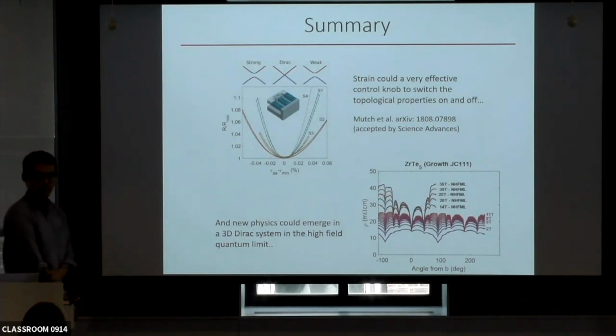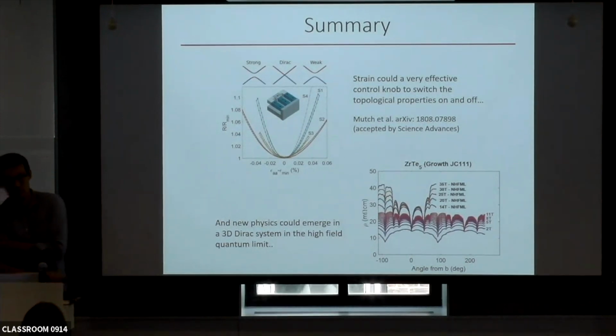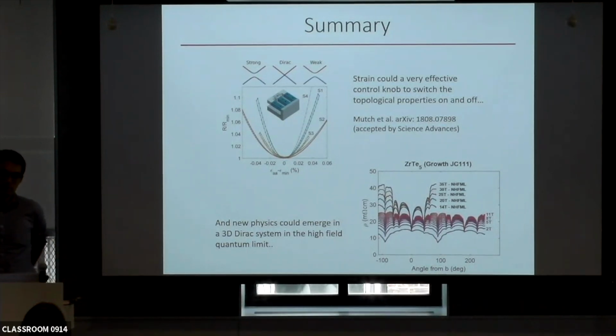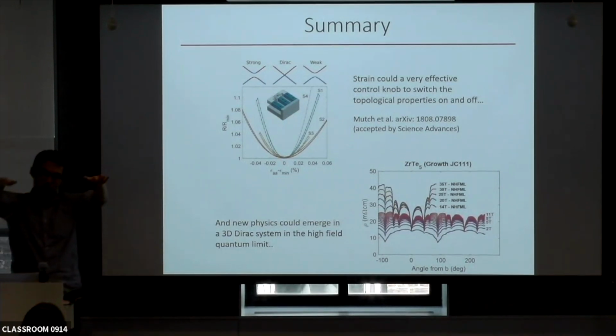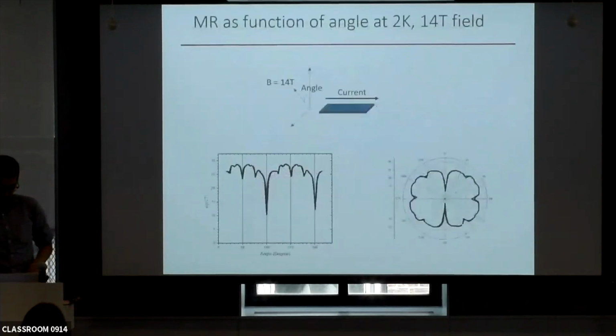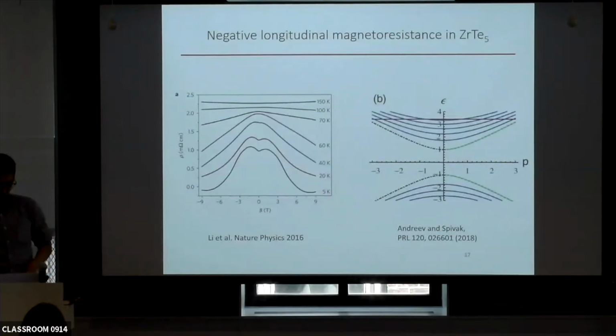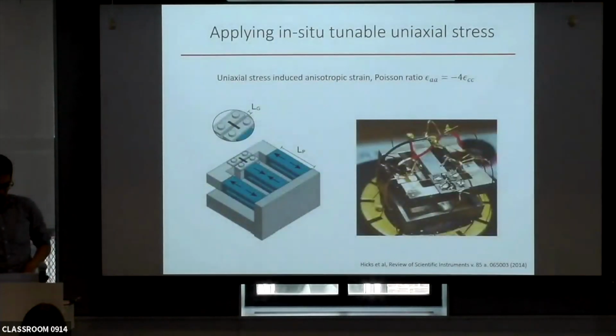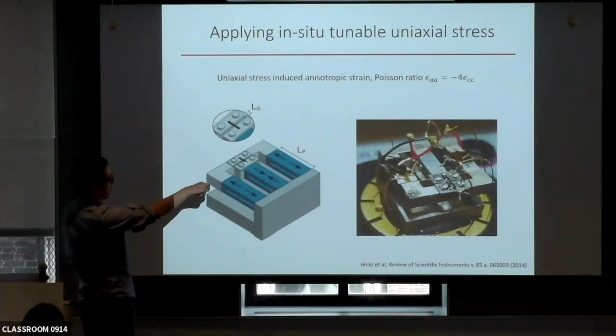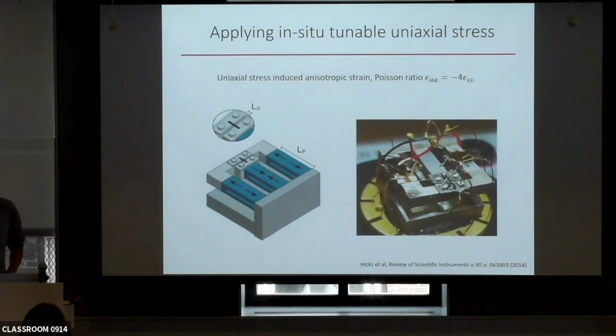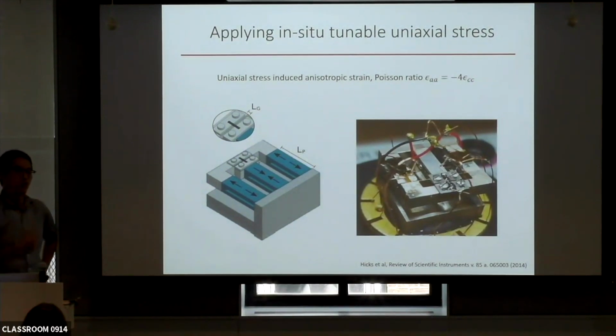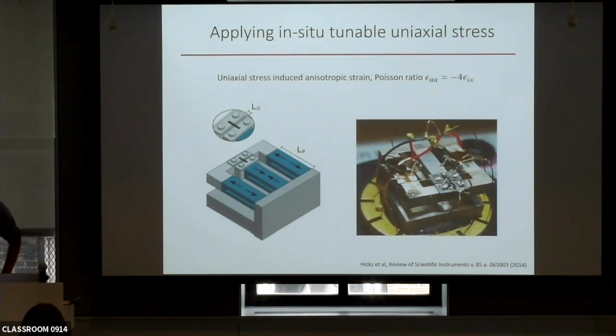Very interesting. On the first part, for the zirconium pentatelluride, as you said, it's a van der Waals bonded material that's very soft. So why does it not glide when you strain it? When you mount the material, you basically apply strain both top and below, so you have epoxy covering the whole crystal. That's right. So when you do these experiments, they're perfectly reproducible. Yes, there's no hysteresis when you swing back and forth, and when you break the crystal, you'll see a crazy effect and irreproducible hysteresis.